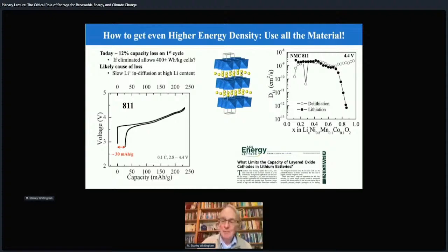And you can think about a lecture theater. If you are sitting in a lecture theater now, if that lecture theater is 75% full of people, then if somebody else comes in, everybody has to move because invariably the empty seats are in the middle. So it's a very similar thing. And taking the lithium out, there's no problem. The diffusion coefficient is the same until the last little bit. So the same analogy with the lecture hall. At the end of the talk, everybody just flows out. So we're trying to solve that, and we're doing some modification of the materials so we can reduce this first capacity loss. We've reduced it by more than 50% at the moment. We think we can get it even lower.